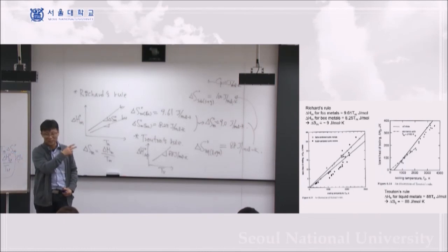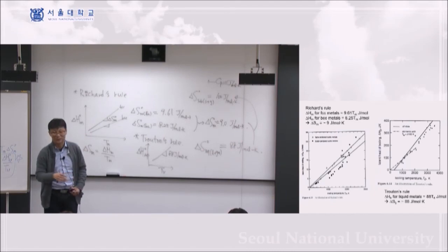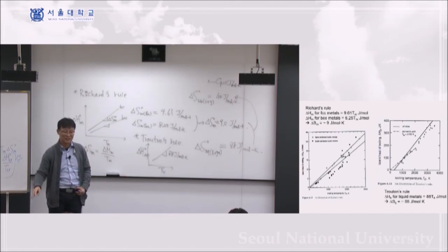Then delta G of reaction is A plus BT, almost constant. There's some change, but roughly, regardless of temperature and more or less regardless of material, if you have solid becoming gas phase, it's about that range. Not like 1,000 or 10, but about 100 or 100 something, plus minus.